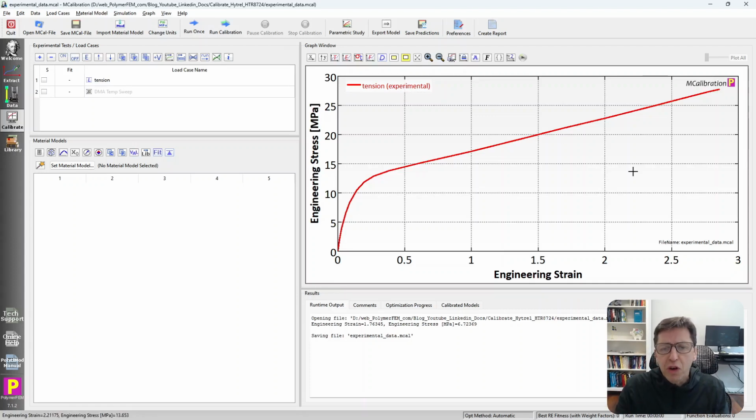So the most obvious material model to try in a case like this is an elastic plastic material model. We have elasticity with very large strains, 200-300% strain. A hyperelastic material model will not be a good idea. Linear viscoelasticity won't work either because we have plasticity. An elastic plastic material model seems like the only choice in some sense because we only have one curve here.